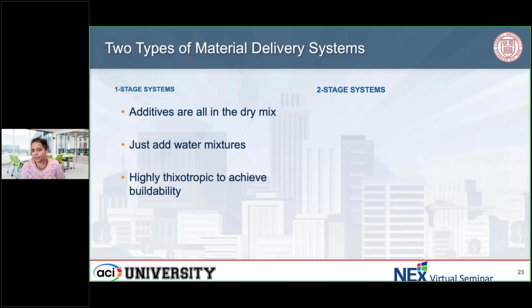I'll go into this a little bit. Basically, what this means is, as you're shearing the system, it'll remain pumpable, but then once you stop pumping, it can hold its shape and have good buildability. So these typically have very short open times because right after you mix the water with the material system, you just want to deposit right away.